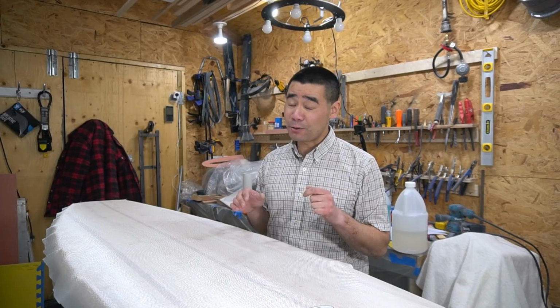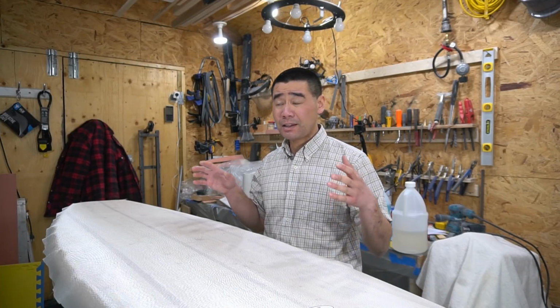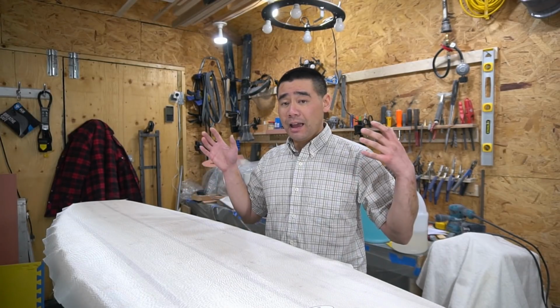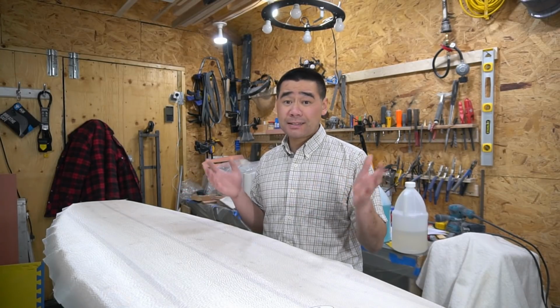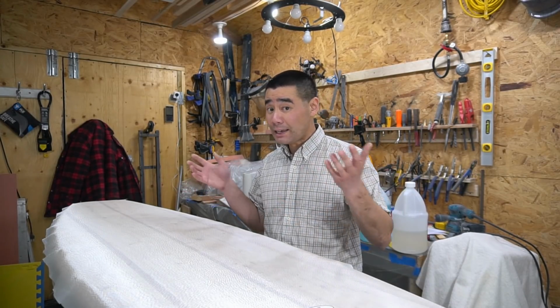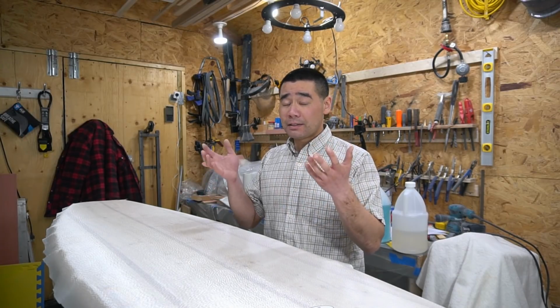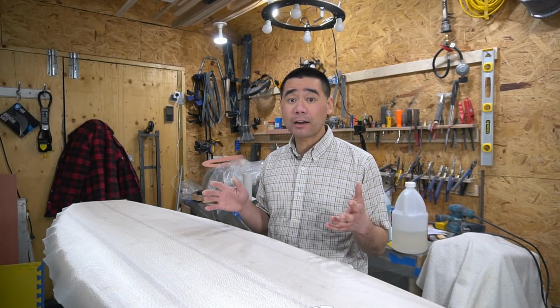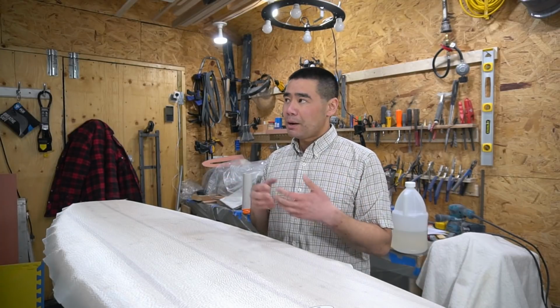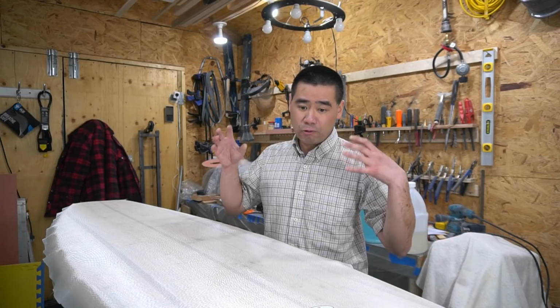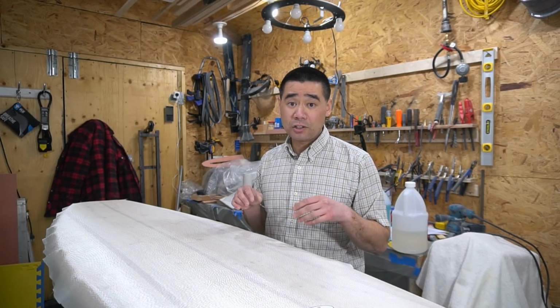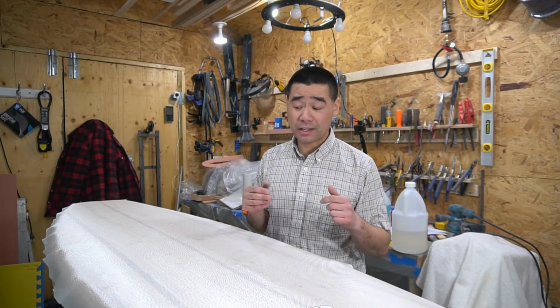Trust me, I know from experience. I had a board one time where I laminated it at maybe 7 or 8 degrees because I didn't have my garage insulated. And it took forever for it to set up. After 2 days, it still hadn't set up. Once I heated the garage and got it all up to temperature, it did cure, it did harden, there was no damage done. But again, the longer it takes to cure, the more likely you're going to get dust and other crap into the epoxy. So that's it for epoxy.